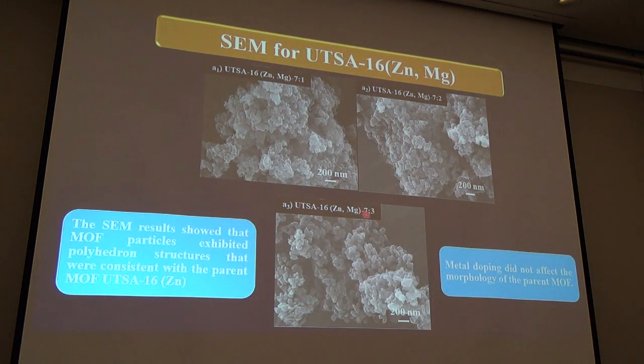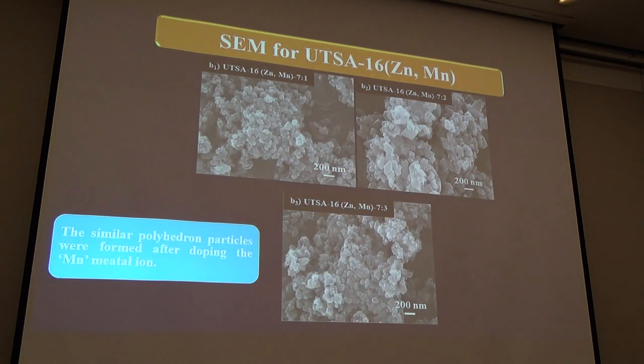The morphology of the MOFs was estimated by using SEM images. SEM results showed that MOF particles exhibited polyhedron structures, which are consistent with the parent UTSA-16 zinc MOF, which was synthesized in our previous study by Mr. Sanjit Gaikwad.